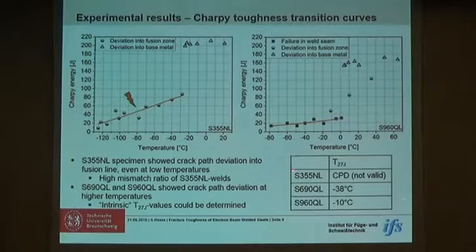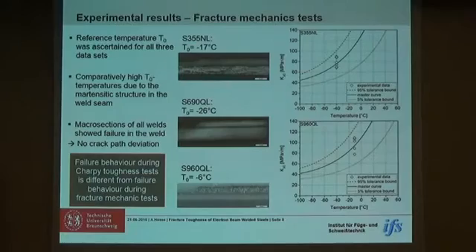This table summarizes the values we found. So for the S355 specimen, we had crack path deviation even at relatively low temperatures. So the T27 temperature isn't valid for our correlation. The temperature that was estimated for the S690 was minus 38 degrees, and for the S960 it was minus 10 degrees Celsius.